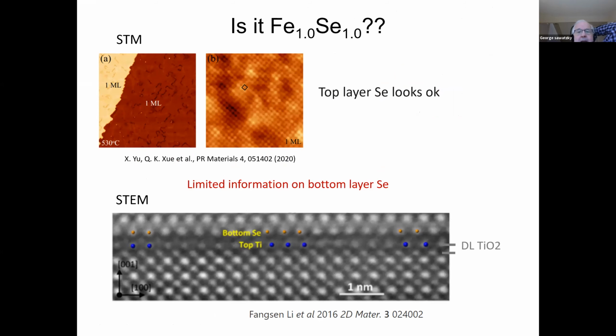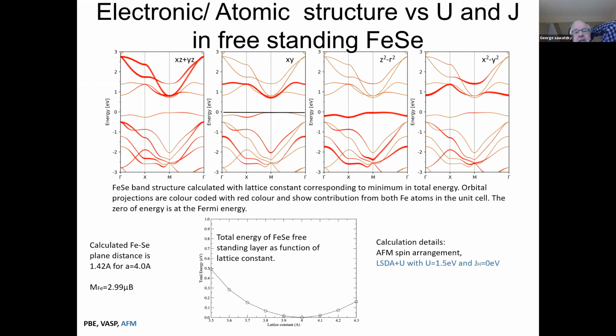Okay, but this is very strange, and this need not be the right answer, by the way, that this is the right electronic structure of this material with this d z squared band here. There are many other examples where we know that if you have these kinds of magnetic moments, then things like multiplet theory become very important. And multiplet theory is something that you can't do in density functional theory. Okay, so it is a purely atomic thing.